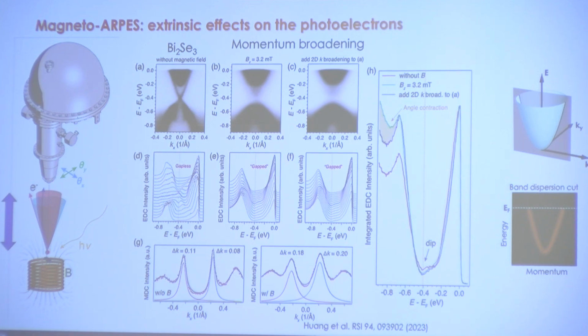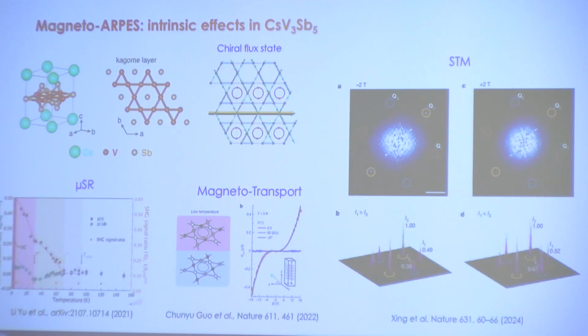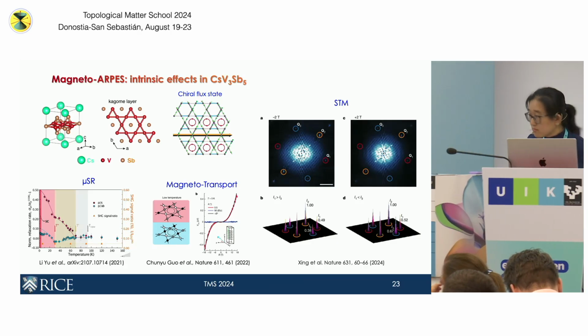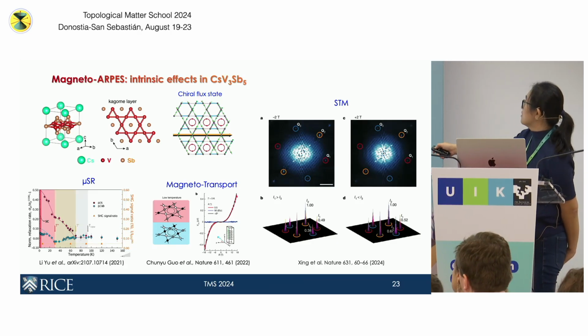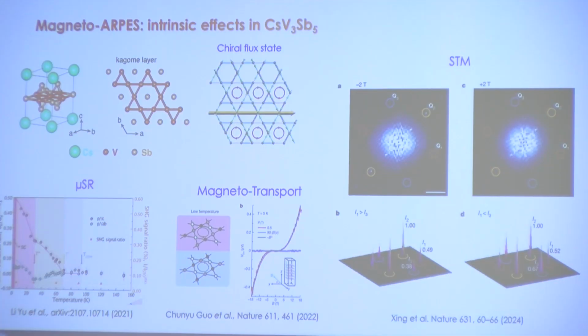So what is this good for? What have we looked at? I'm going to show you one example. This is the famous material that Stephen talked about, and I guess Vidya will also talk about tomorrow. This is the Kagome system, cesium vanadium-3 antimony 5. It's interesting because, as Stephen has already gone over, it has a charge wave that is associated with a chiral flux state. So there are potentially loop currents that break time reversal symmetry. And many probes have seen an effect that suggests time reversal symmetry breaking.